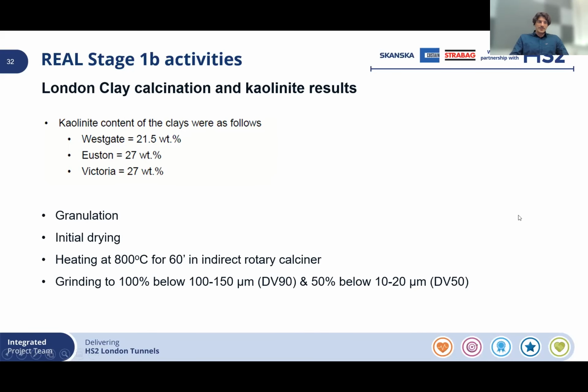So some of the initial results that we obtained, we were happy to see that we have more kaolinite content in the samples that we're investigating as part of stage 1B. We can say that this was somewhat expected due to the variability of London clay across the London basin area. And our work involves granulation, drying, heating, of course, calcining in a rotary calciner, and grinding to a specific particle size distribution. Next slide, please.